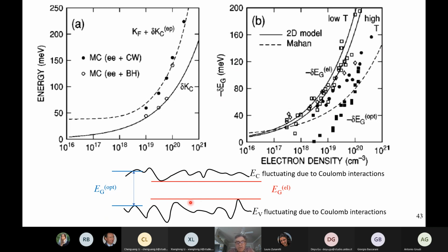And the reason is illustrated in this figure, which also will let me introduce another thing related to the calculations that are shown here, done with the semi-classical Monte Carlo calculation. The optical gap is essentially the minimum gap that you can see. Sorry, the electronic gap. The optical gap is some sort of an average direct gap. What I show here, the x-axis should be viewed as position. These are the fluctuations of the potential due to the random fluctuations of the electron density and impurity distribution. Time average of it, so it will be the impurity distributions. And the electron density also fluctuates as well.